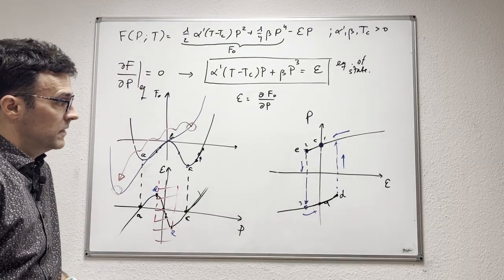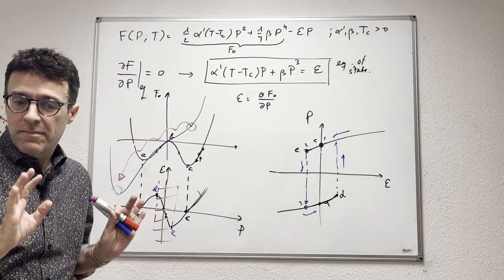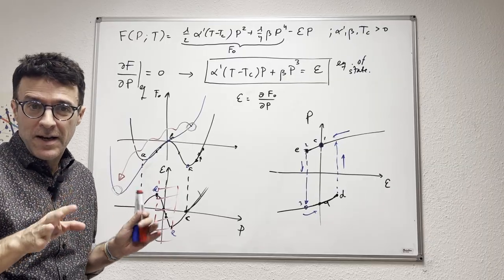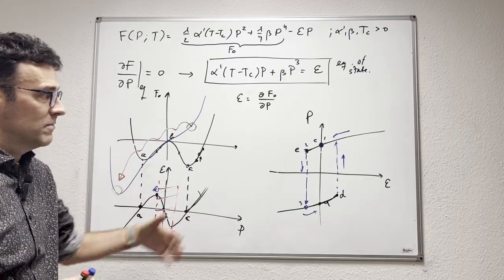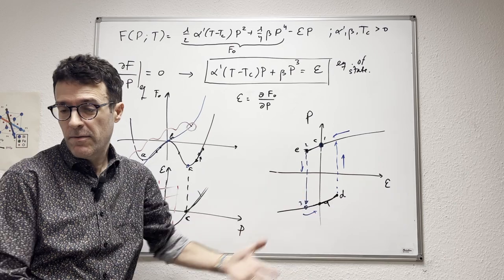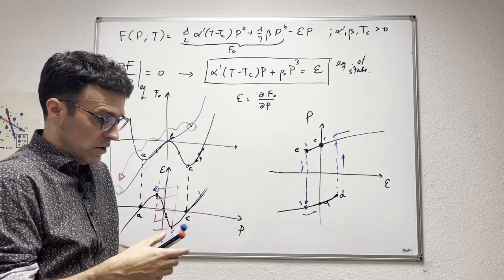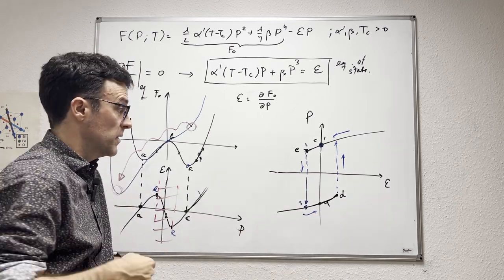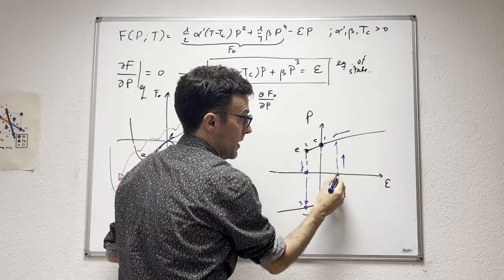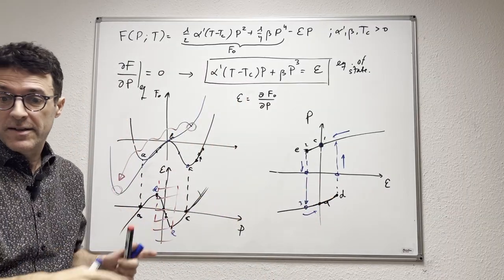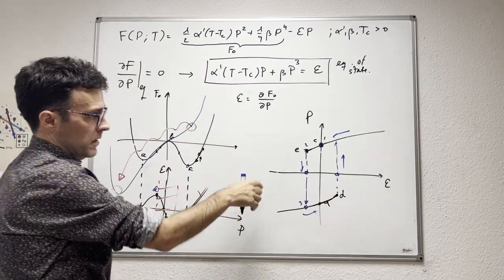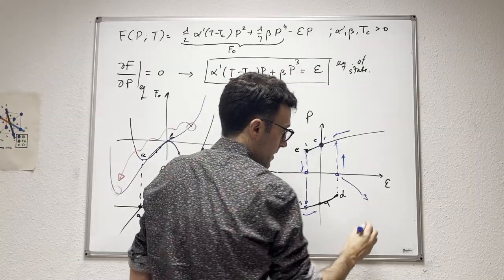So you can see our theory was hiding also the answer to hysteretic behavior under field switching. Of course, it gives us a very specific prediction for the electric field we need to apply to destabilize the minima. This is what we would call the coercive field.